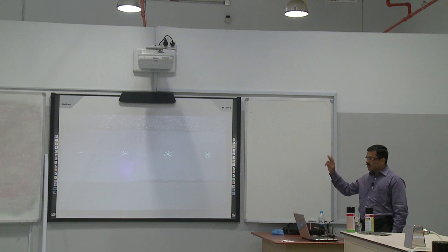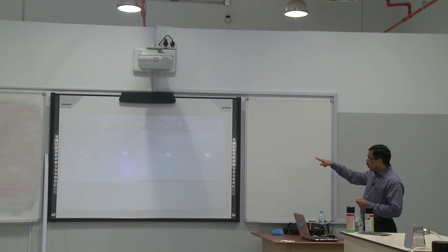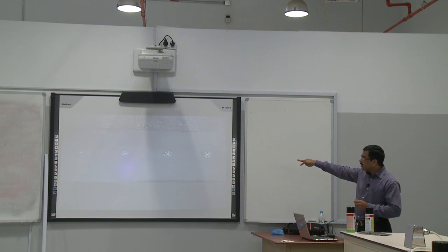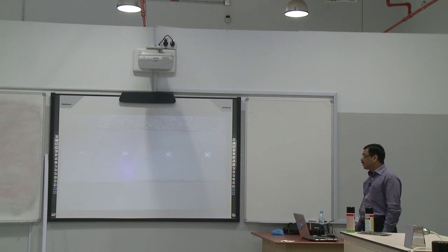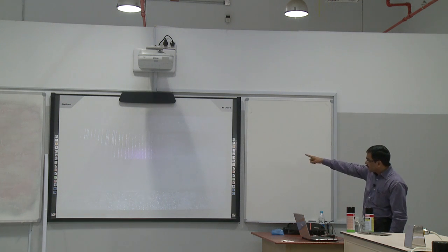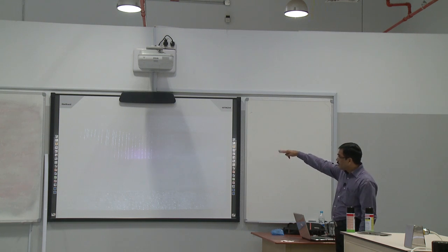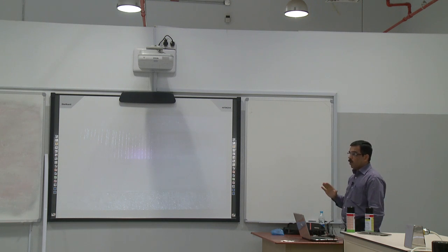Same type of blocks. This is for the comparison of old and new chemicals. Because this is actually two pieces, one piece and another piece. If it is showing all equal, that means that is good. Both the chemicals are in good condition. See, this side the indication is not clean. That means that chemical is contaminated. Whichever shows the indication, that means that chemical is still okay.